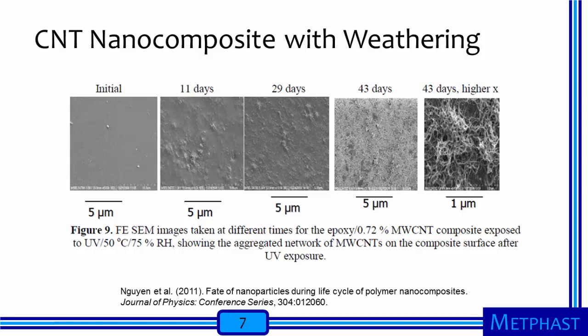This figure from their paper shows images of the surface of the nanocomposite material taken at several intervals during the test. The multi-walled carbon nanotubes start to become visible after 11 days of accelerated aging, and the concentration of the nanotubes at the surface increases over time. By the end of the test period, the surface appears to be a mat of carbon nanotubes.